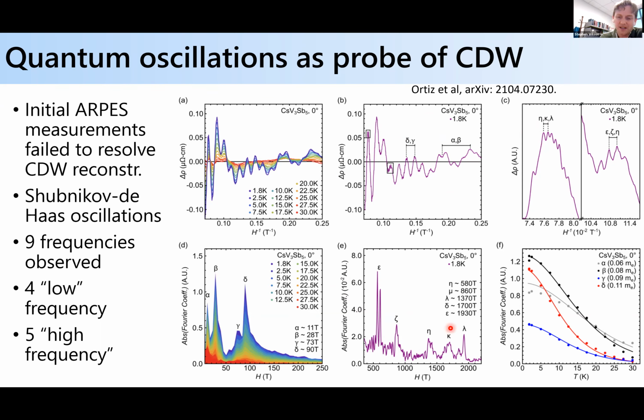So these high frequency components get rapidly damped out as you heat up the sample. So we can't really track the power spectrum as a function of temperature, but the low frequency orbits we can. If you fit these low frequency orbits as a function of temperature, you can basically back out an effective mass. They're all about 1/10 of a free electron mass. So it's very light electrons, consistent with perhaps their origin being from the Dirac points near the vanadium, due to the vanadium orbitals in the system.